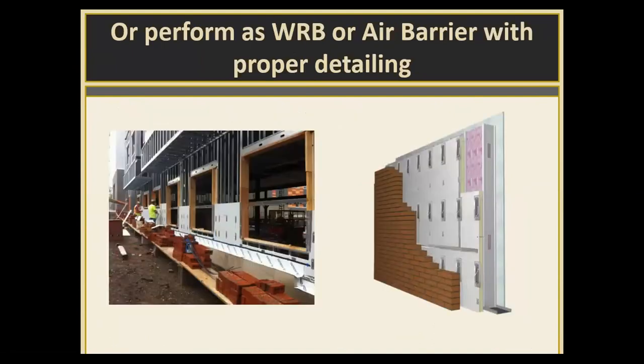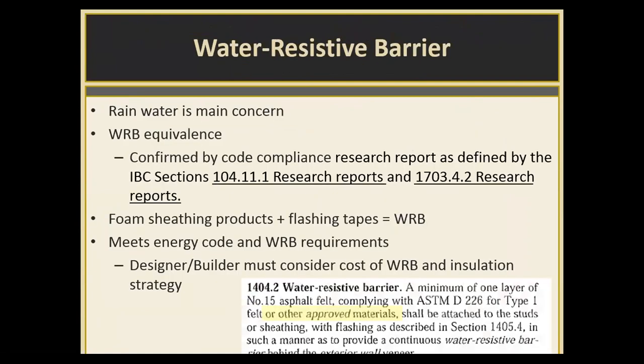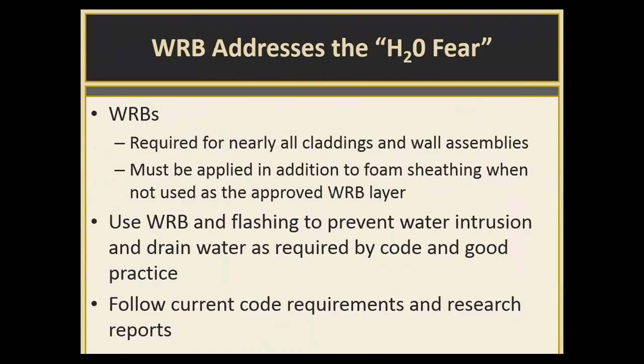As mentioned earlier, polyiso foam board can also be used as the water-resistant barrier or air barrier with proper detailing as well. For water-resistant barrier functionality, bulk water is the main concern, and you need to make sure if it's going to be used in that fashion that proper flashing tapes or seam sealants are used, and those seam sealants are the ones that have been tested with the material. WRBs are typically required for almost all wall assemblies, and they just got to provide good drainage. It's important because buildings are meant to keep the water out, and that's an important component in the overall assembly.